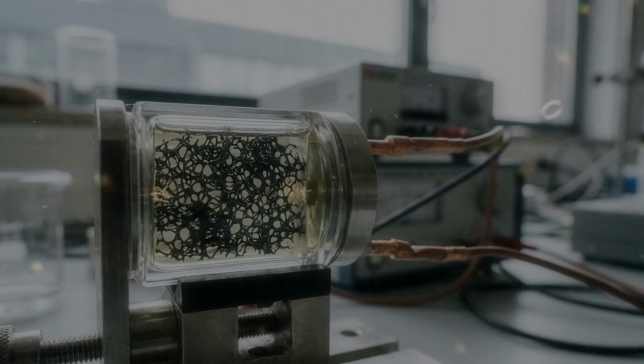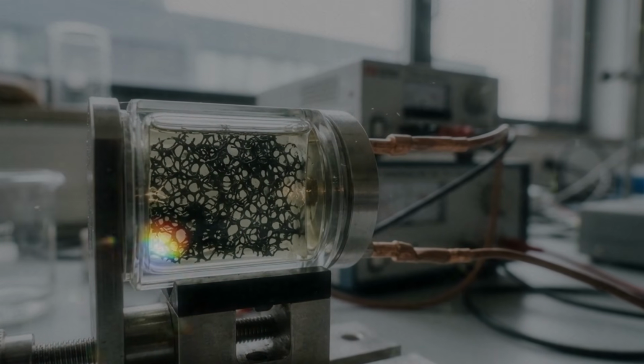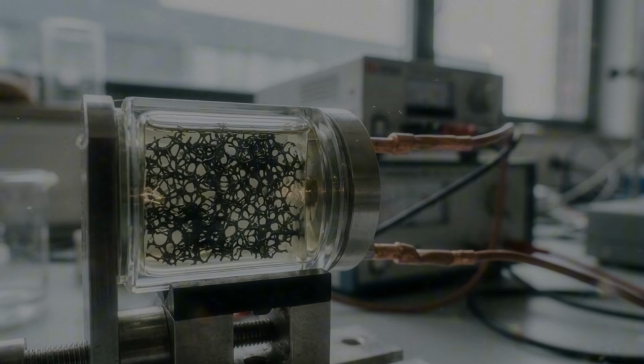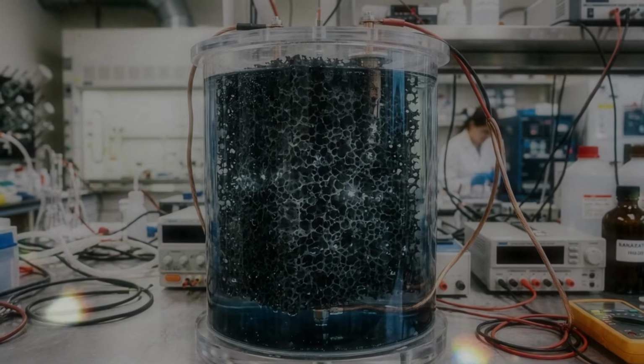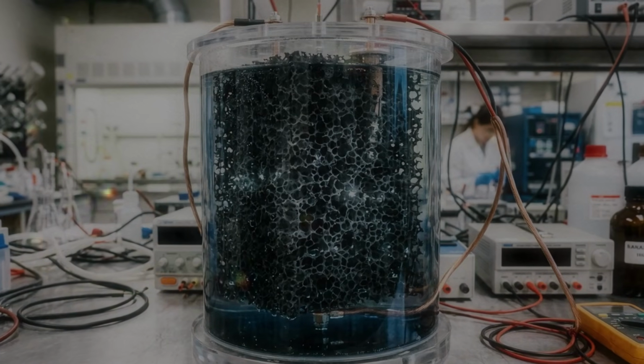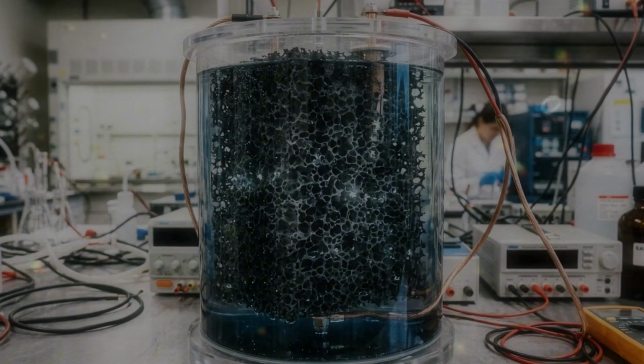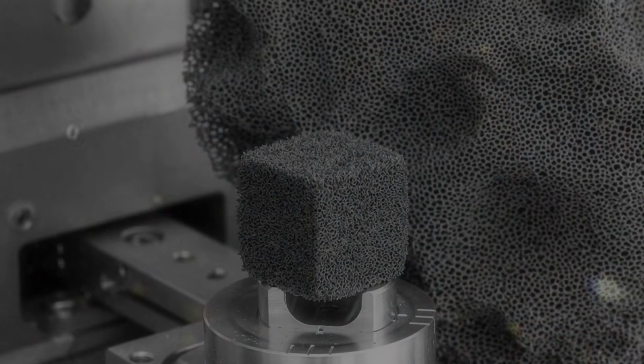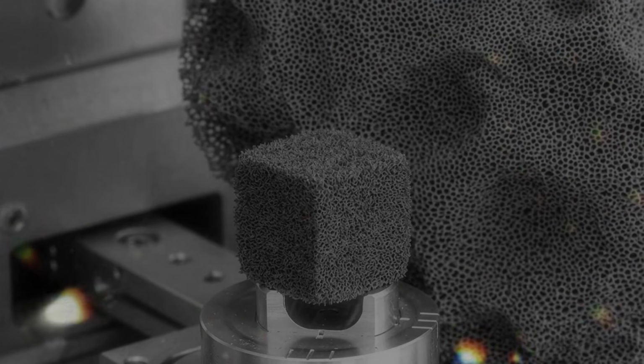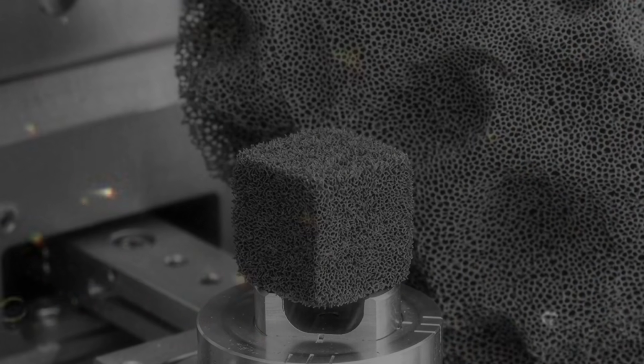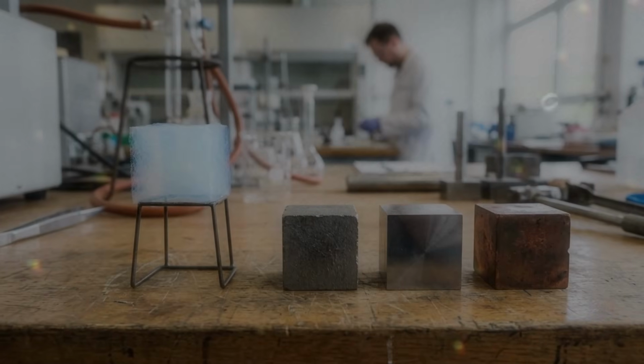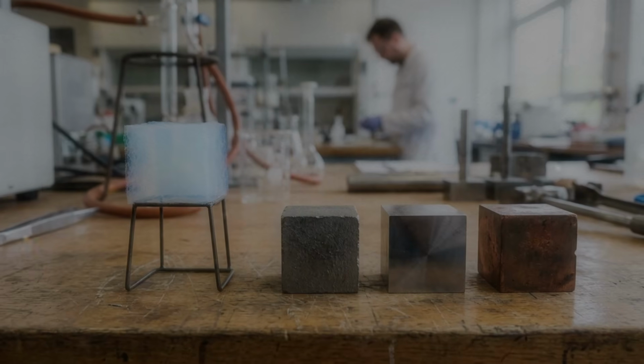Differences in expansion can create stress during heating. Adhesives can fill the pores and add unwanted weight. Cutting can damage the surface. For this reason, aerogels are frequently built directly into a larger structure. Silica aerogel can form around fibers. Graphene material can grow on a foam. A wet gel can be cast onto a fabric. The connection develops during manufacturing instead of being added afterward.